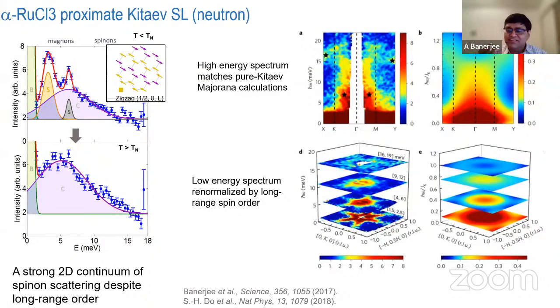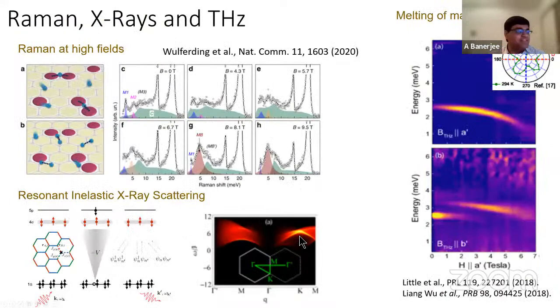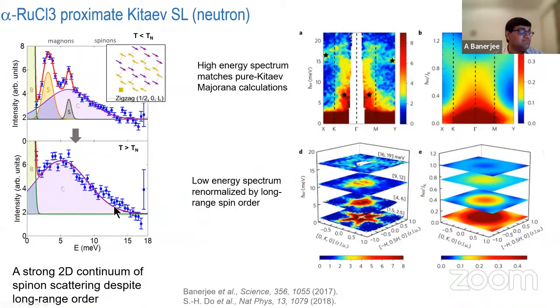But the goal was that we are very close to the Kitaev state. Can we nudge this material a little bit to make it go to the pure Kitaev state? And then there were several experiments which happened. There are probably now 200 papers which came out after our discovery, which included terahertz measurements, Raman measurements, resonant inelastic X-ray measurements, all of which confirm that you see this itinerant, broad continuum of scattering, and this broad continuum of scattering actually comes from Majorana fermions, this itinerant Majorana fermions that we talked about.